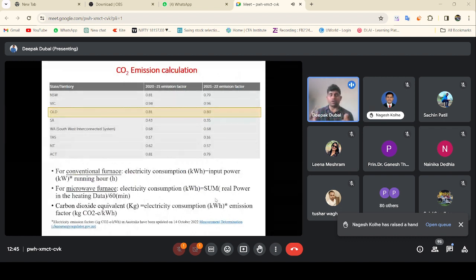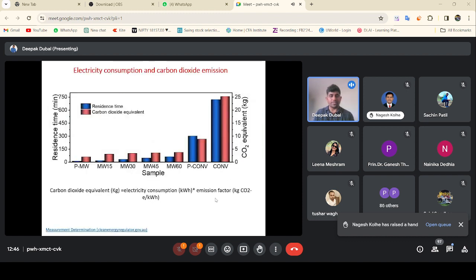So as we started to talk about carbon dioxide emissions, we wanted to explore, if we use the conventional furnace, how much carbon dioxide emissions we are contributing. And if we replace the conventional furnace with microwave furnaces, are we reducing the carbon dioxide emissions? So what we did is, this is something which we found on the Queensland government's website, where based on the energy input to the furnace, we can calculate the carbon dioxide emissions. So you can see here, we have calculated the emissions which we generate by using the microwave process and the conventional process. This is the residence time, and you can see with the microwave, we are contributing a really very small amount of carbon dioxide emissions to the environment as compared to the conventional furnaces.